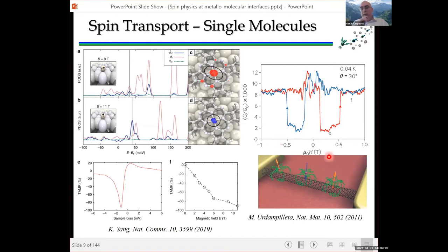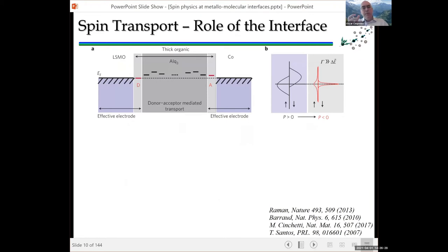What people very quickly realized is that these effects were very difficult to reproduce, of course, in particular for single molecules, and very dependent on how everything was being done. So the role of the interface, as we have seen, at the interface between either the metal, or in this case, the magnetic oxide, and the molecule, there is going to be charge transfer, there is going to be rehybridization, there is going to be the formation of a dipole, and the doping with the spins of the molecule. So depending on what you have in your interface, you are going to have a very different effect.